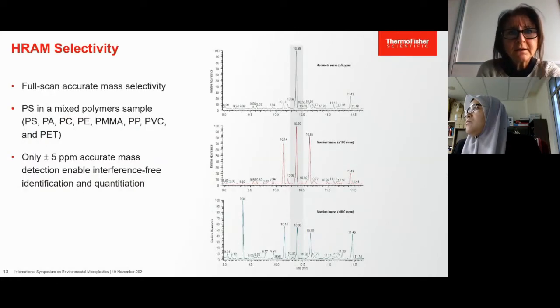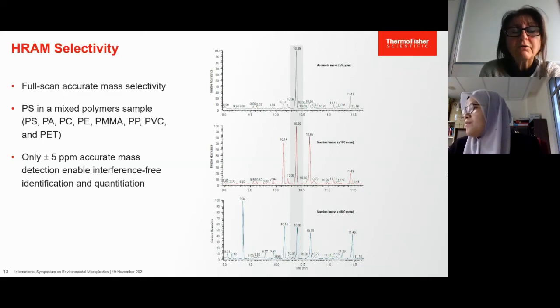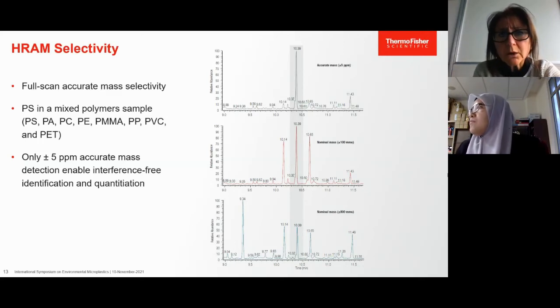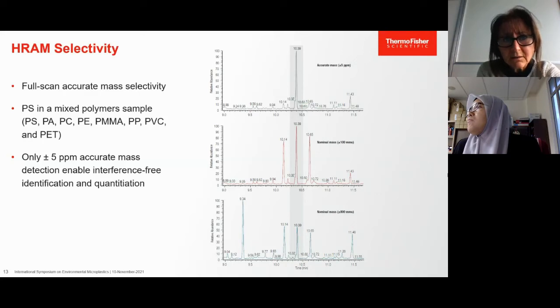Another example of full scan accurate mass selectivity is shown here for the polystyrene in a mixed sample containing the other 7 different polymers. Accurate mass measurement enables extraction of accurate mass within a window, in this case of ±5 ppm, as shown in the top chromatogram. And this is ensuring confident detection. With the 2 chromatograms below, we could simulate a nominal mass acquisition with an extraction window respectively of ±100 millimass unit in the center and ±800 millimass unit at the bottom. In both cases, there are additional interfering compounds, and this is impacting on the identification and on quantitation.